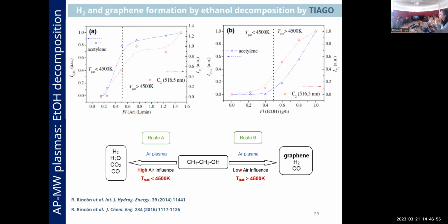As I said before, there is a relationship between the production of C2 species. Here you have in red C2 species in the plasma, and also acetylene formation as gaseous byproducts. As I said, under certain conditions where gas temperature is lower than this value, we don't have a large amount of C2 species, and the formation of acetylene is limited. But as soon as we increase this plasma gas temperature, acetylene appears as well as C2 species. So keep in mind that C2 species and acetylene and graphene are correlated.